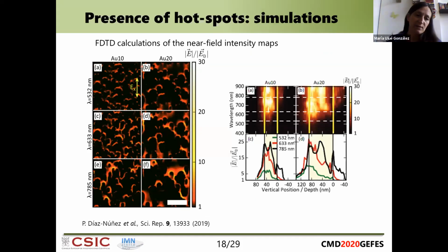But in the simulations, what we did was to try to see the dependence of this enhancement with the wavelength, because usually when you design, for example, stars or nanoparticles for SERS with a very strong field enhancement, they have a resonance at a very well-defined wavelength, so the SERS works very well at that wavelength. But this will be a much more broadband system because we have so many different interactions and nanocolumns of different size. So we tried to see if the spectral response was actually much more broadband in that sense. So what we saw from the simulations is that the value of the enhancement increased as the wavelength increased actually, and also it increased with the length of the nanocolumns.